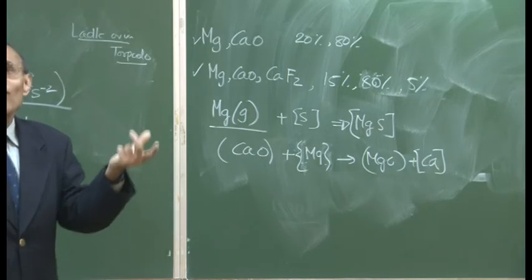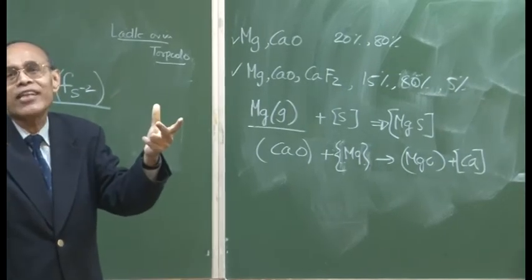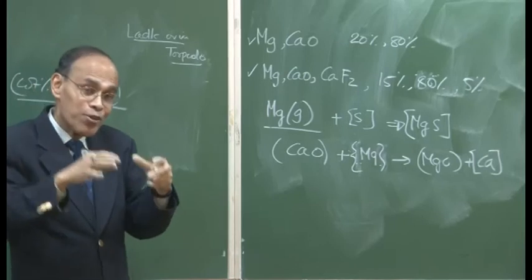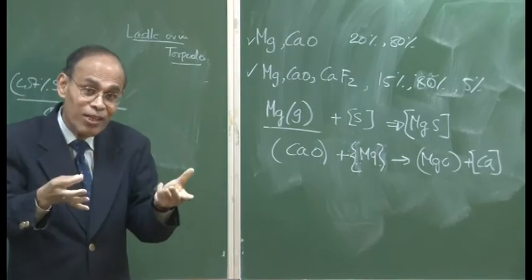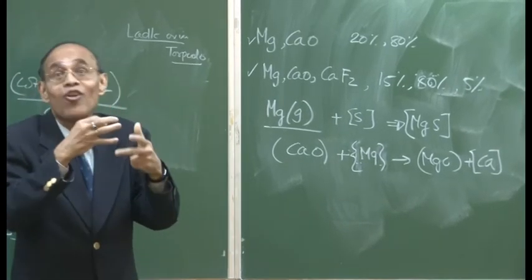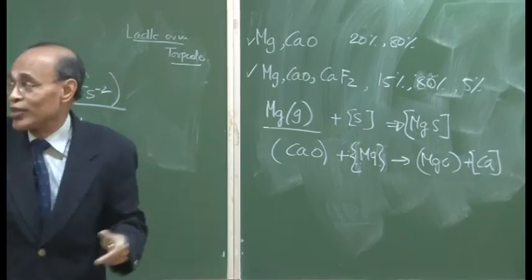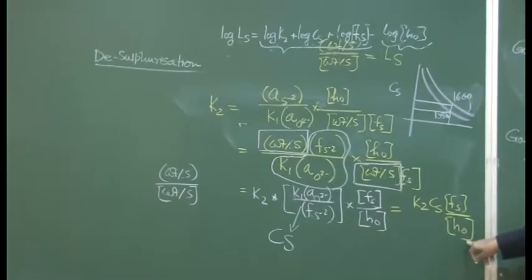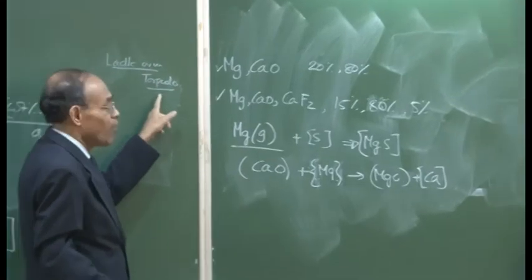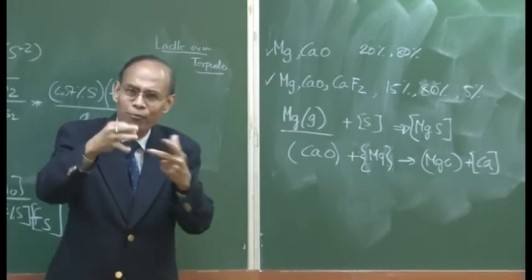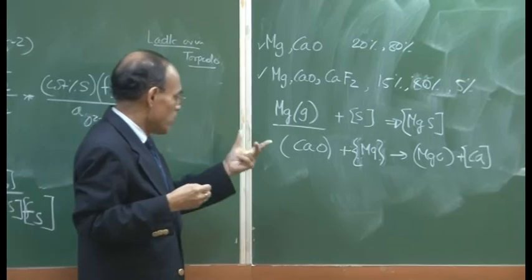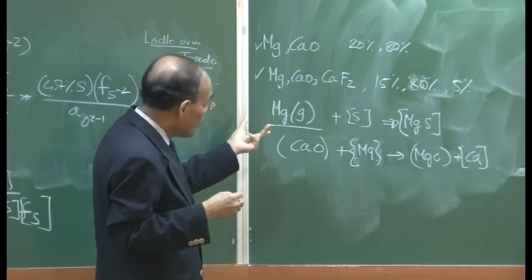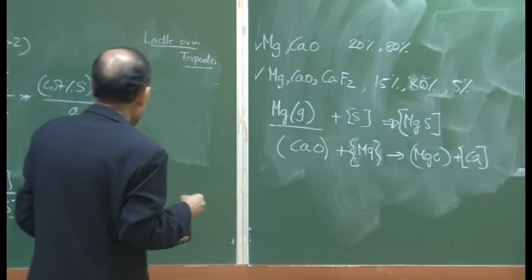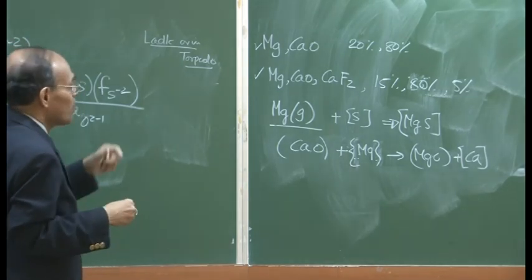And we know that already we have a very high carbon content in the melt itself. So, high activity coefficient of sulfur in the metal phase and a reducing environment are all ensured in the melt phase itself. So, we do not have to worry much about the oxygen potential parameter, which itself is extremely small. So, what we have to ensure now is that we maintain a basic environment, and we maintain sufficient fluidity of the slag. And why do we want to maintain fluidity of the slag?